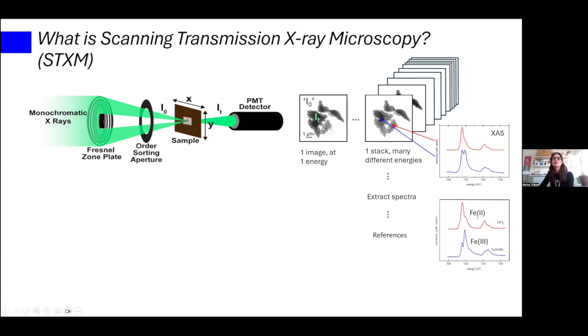Again, you can do this by eye, just qualitatively, saying, well, the top one kind of looks like Fe2+, and the bottom one is much more like a mixture of the two. But you can also do it by fitting or, again, some sort of more advanced data analysis. But in a nutshell, this is then how you find out what is going on in your sample. And you can plot it in the end by saying, okay, where is now my Fe2+? And you can have it in a quantitative way, this being the quantitative scale of nothing at all to very much. And of course, you can put numbers on that. But you can plot it to say, this is the Fe2+.